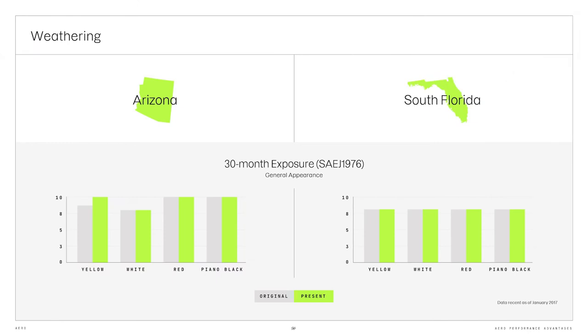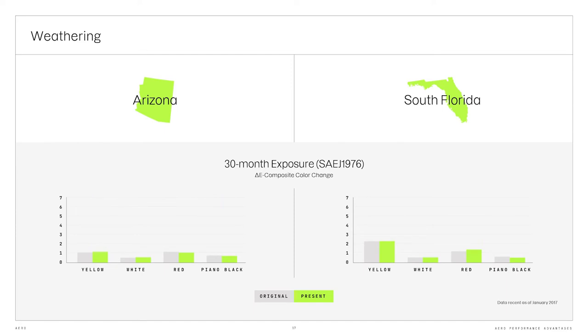So the weathering characteristics. Initially, after validating our tech in motorsports, we started the initial testing in Florida and Arizona that we all use on paint. And after 3 years, it was pretty obvious we were equal to or had a significant advantage. But if you go back to our first live experimentation, it's really a horizontal surface. The downside, the Achilles heel of previous film technologies is based on horizontal performance, whether it's a water spot, gloss degradation, cracking. In 2013, we did an experiment based on horizontal weathering, where we actually did a contrast roof on a Range Rover Autobiography and parked it, and it never saw one day in a garage in 5 years in Marin County, California, which has sun 95% of the time, direct sunlight.